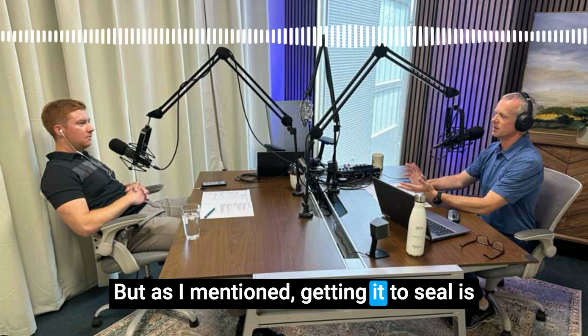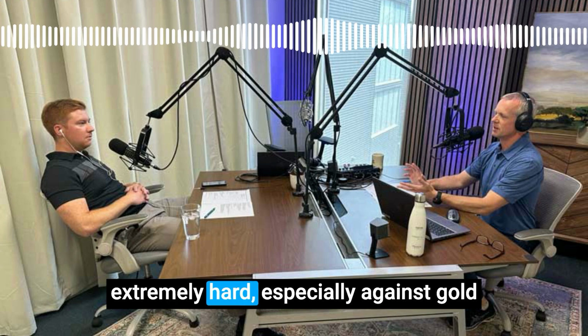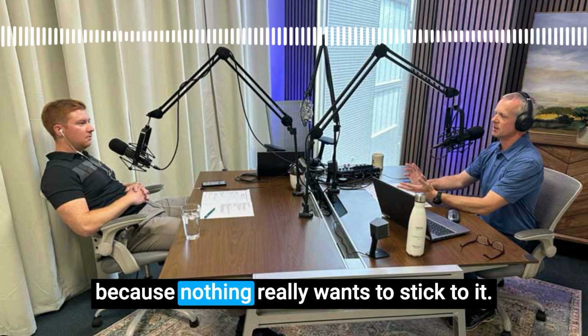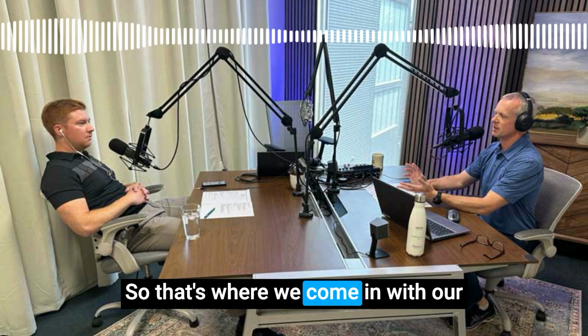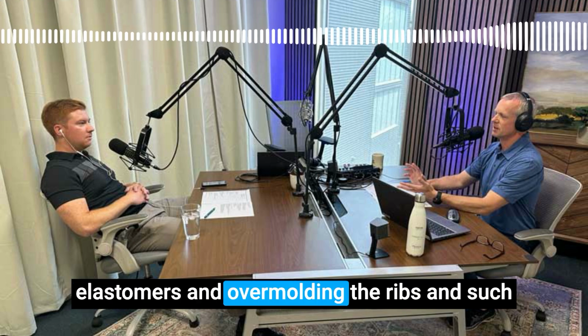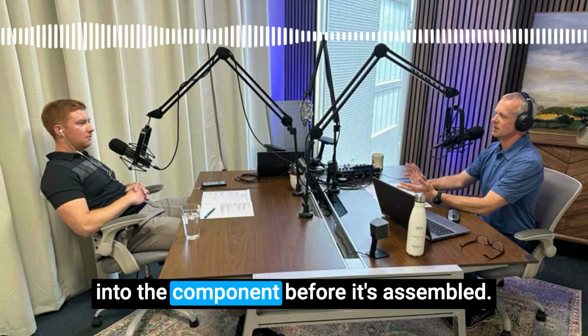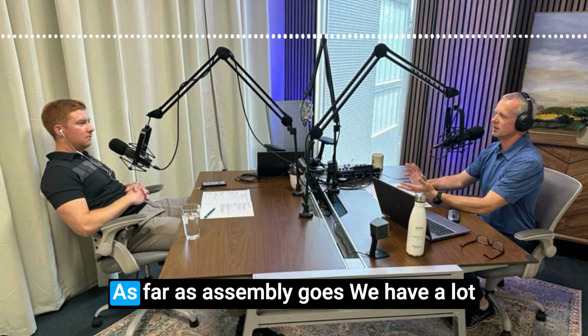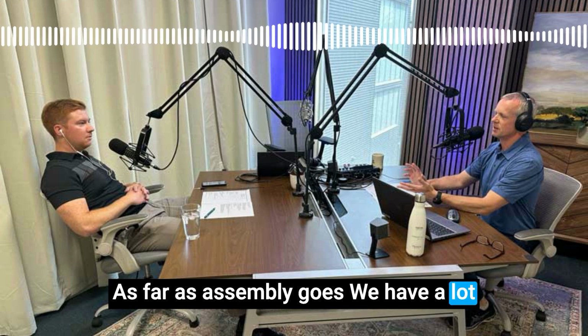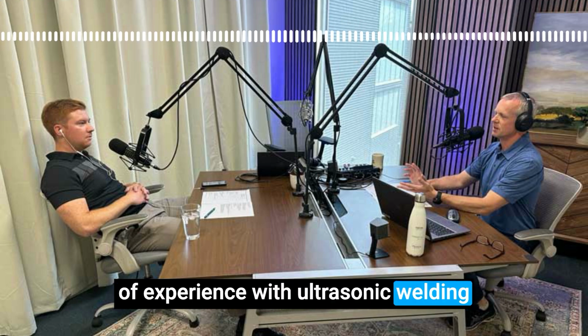But as I mentioned, getting it to seal is extremely hard, especially against gold, because nothing really wants to stick to it. So that's where we come in with our elastomers and overmolding the ribs and such into the component before it's assembled. As far as assembly goes, we have a lot of experience with ultrasonic welding, and